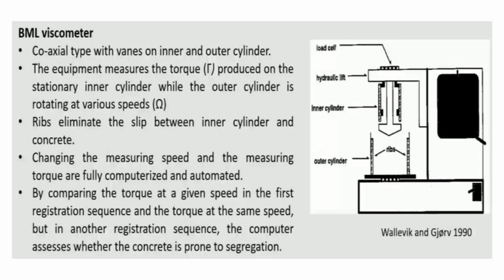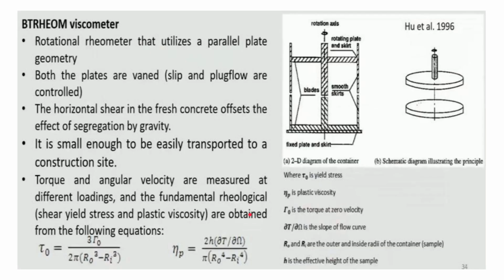By comparing the torque at a given speed in the first registration sequence and the torque at the same speed in another registration sequence, the computer assesses whether the concrete is prone to segregation. So basically, if the speed is constant, the torque should also be constant, right? But after changing the registration sequence, if the torque gets changed for the same speed, mainly if it has become low, that means segregation has occurred in the concrete. So using that, we can check whether the concrete is prone to segregation. That is the use of the BML viscometer.